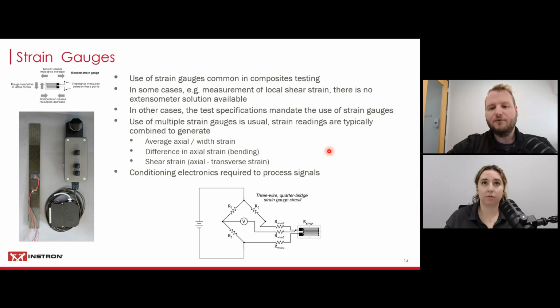Strain gauges themselves need to be used with the appropriate conditioning electronics in order to process the resistance change and then take that to calculate your resulting strain. It's pretty common to use multiple strain gauges at once, and those readings are typically combined, and then you can generate things like the average axial strain or width strain of your test.